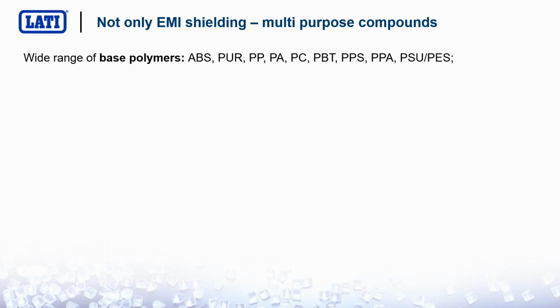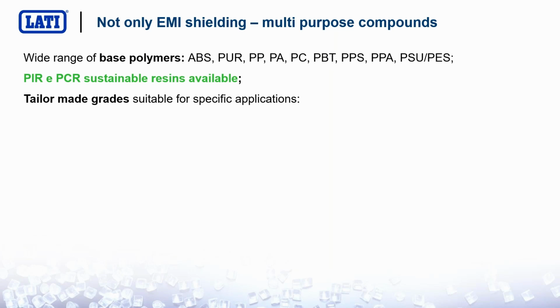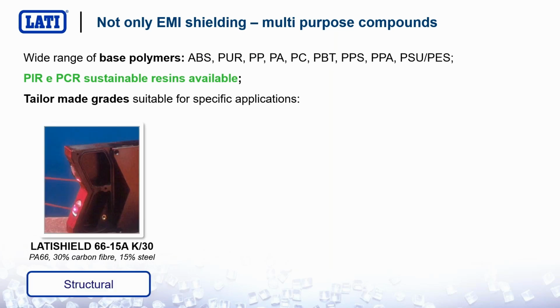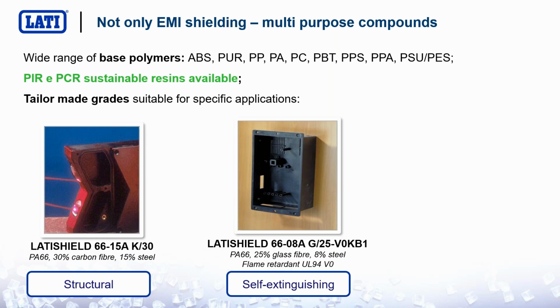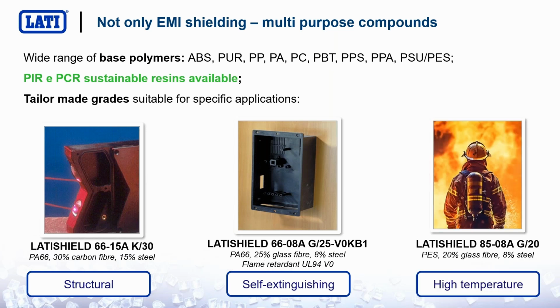It's also very important to stress the fact that EMI shielding compounds may be designed not only to be EMI shielding, but also to provide other properties. By selecting the base polymer, you can have plastic parts that can withstand high temperature, right up to 200, 250 degrees. By selecting the right polymers, you may also have sustainable applications, like those using post-industrial recyclates or post-consumer recyclates. And don't forget that we can tailor-make compounds for your requirements. Just to give you an idea, we can provide steel-filled compounds featuring carbon fiber, so structural and shielding for very demanding applications from a mechanical point of view. We can provide flame retardant shielding solutions and high temperature shielding solutions. Just go and check our website or drop a line to our technicians to have a nice overview of our shielding materials.